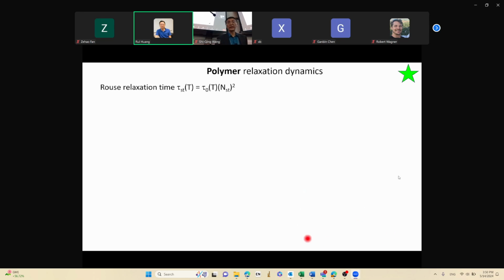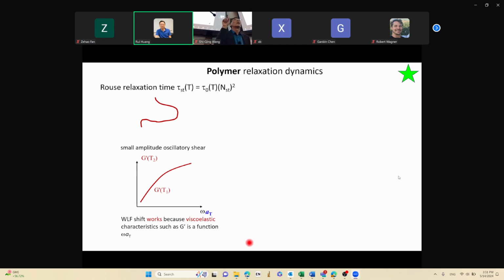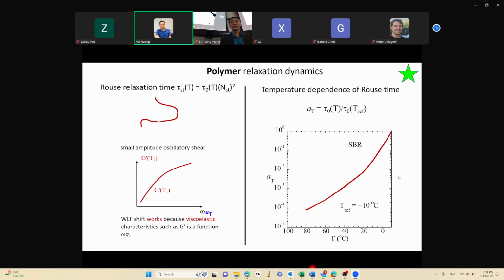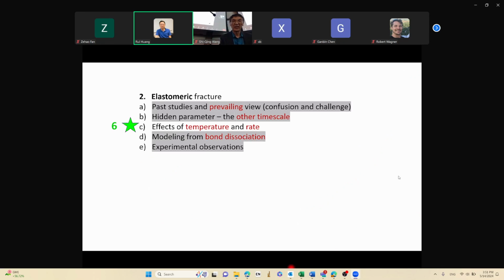In any case, let me go through this whole thing for you one more time. There is the polymer relaxation dynamic. This is how the chains relax. I'm just picking up the chain, and you find out the relationship with respect to temperature. Well, this is one temperature, this is another, and then they shift. Why can they shift? Because that function, the so-called storage modulus, indeed is only a function of the product of the frequency times the relaxation time. Therefore, it works. So you can do detail and find indeed WLF type thing.